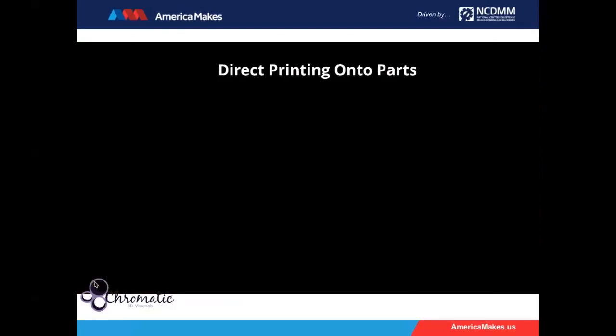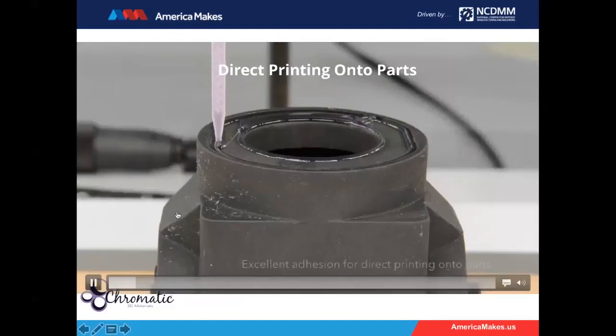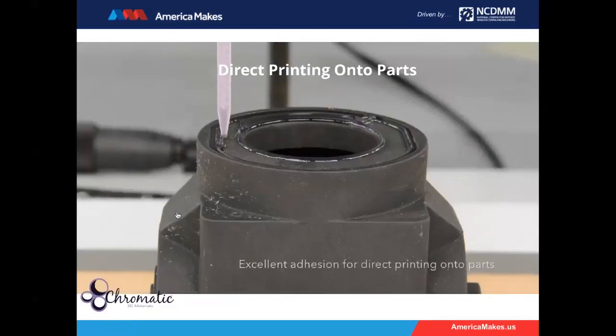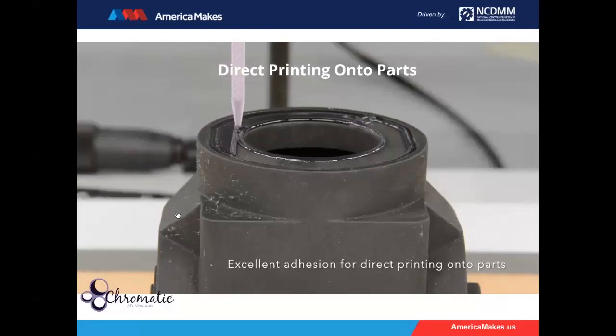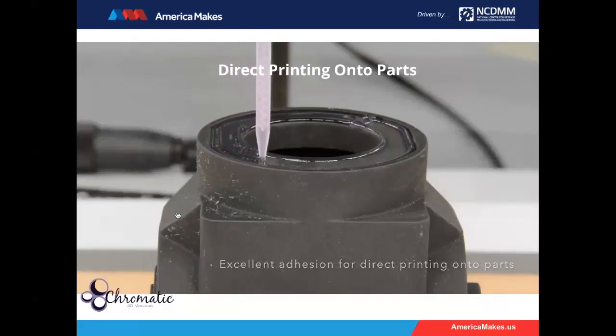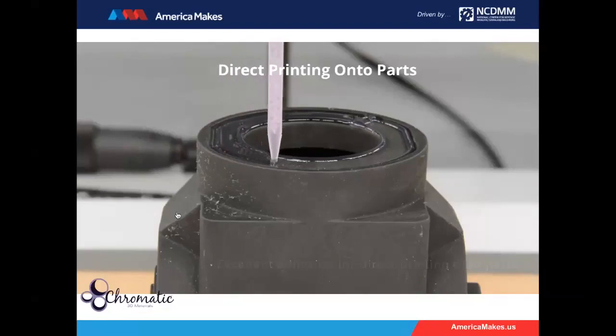Taking this a bit further, another element we can do is directly print onto parts. The reason why this becomes so important is because of two attributes. One is the adhesion of the reacting material allows it to adhere very strongly to metal substrates, to other plastic substrates, but also an important element is that the printing can happen at room temperature. So in this video, what you see here is printing onto an ABS printed part, but because the printing happens at room temperature, we're able to add this elastomeric gasket to the part without having to fear melting of the ABS. But this could also be on a metal part. And I believe that this flexibility of the printing method allows you to really open up new designs. You don't need to worry about how to bring these parts into the printer.